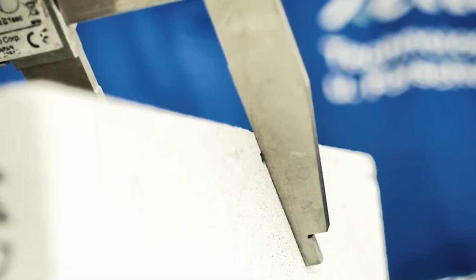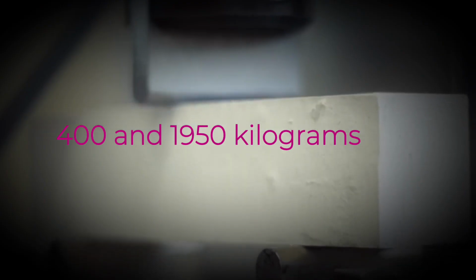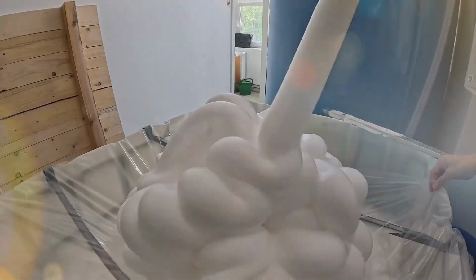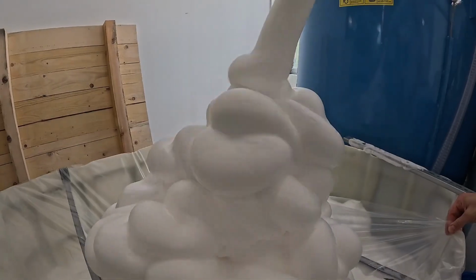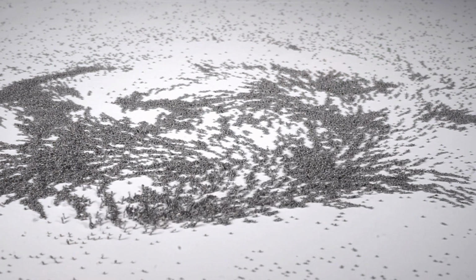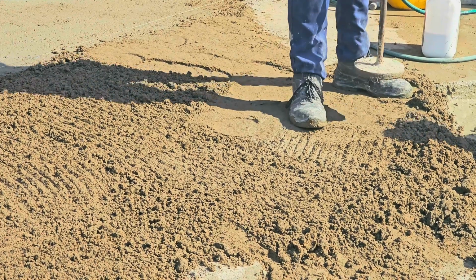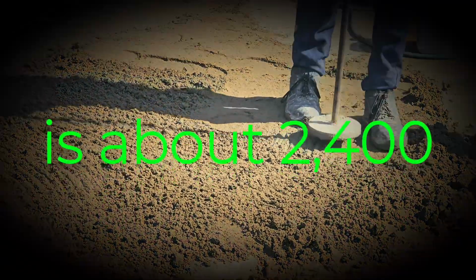Conventional foam concrete runs somewhere between 400 and 1950 kilograms per cubic meter. Working with stabilized foams, researchers have gone under 300. One published result using treated nanosilica held inside a viscous gel came in at 80. Ordinary structural concrete is about 2,400.